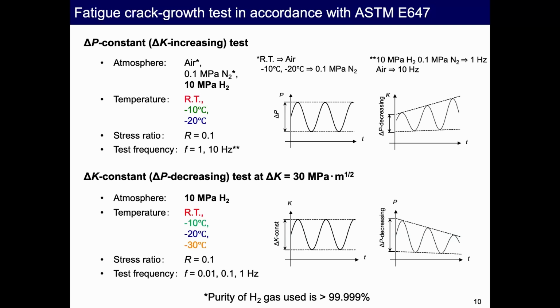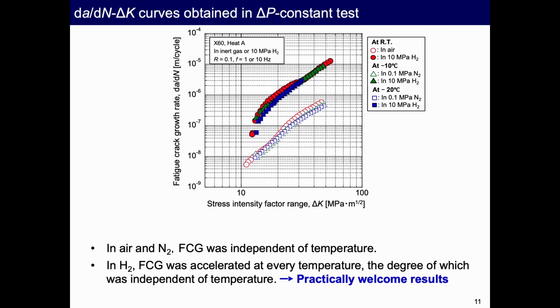One is a delta P constant test at 3 different temperatures to obtain the da/dN and delta K data. The second one is the delta K constant test to obtain the relationship between the acceleration ratio and frequency, also at various temperatures. This is a result, da/dN and delta K curves obtained in the delta P constant test. As you can see here, the open marks show the experimental data in air. So crack growth was independent of temperature.